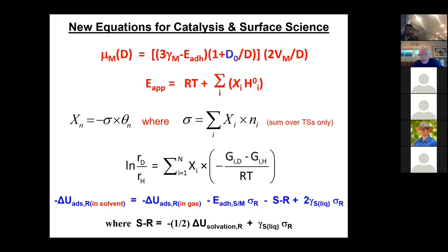I will say, though, that our experimental evidence is as follows. In the gas phase, whenever we measure the heat of adsorption of these kinds of molecules, or almost anything for that matter, unless they're things like water that want to make islands, most adsorbates that aren't doing strong hydrogen bonding, because of their interaction with the surface, have a downward, usually, or sometimes upward pointing dipole moment.